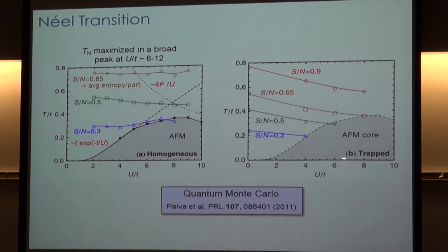It's a little bit different in an inhomogeneous system. In an inhomogeneous system, you can have entropy that varies spatially. So you can have the entropy migrate out to the edges where the density is low, leaving the entropy in the center to be lower.